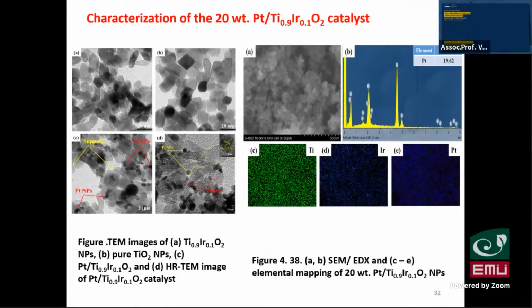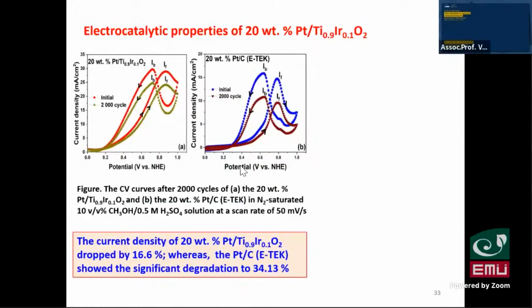We also disperse platinum on our support and apply it for methanol oxidation. We can see our catalyst shows enhanced stability and activity compared to commercial catalyst.